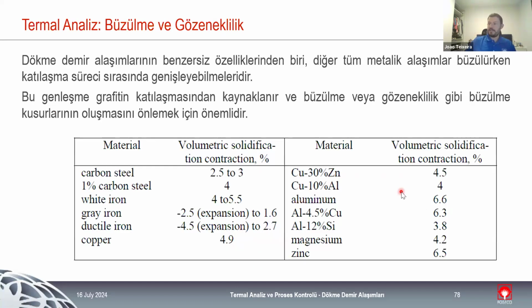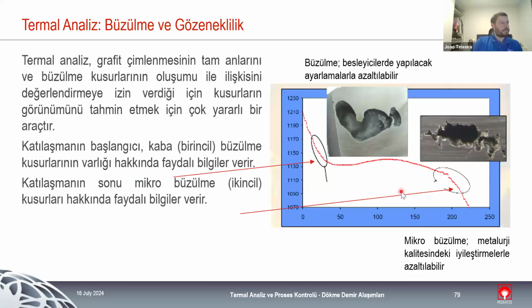Of course, we can counteract this problem in the particular case of cast iron because we have graphite, and graphite is the only element that expands during solidification, and we can use that expansion to counteract the problems of shrinkage and micro shrinkage. If we are dealing with steel, for example, or with aluminum or copper alloys, we don't have anything that is expanding during solidification. Everything is contracting. So we need to be even more careful when we are going to design the gating system and all the systems to feed the die.